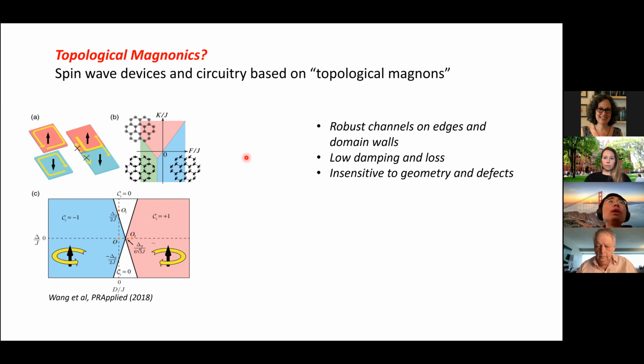This is due to something intrinsic to magnonic systems: in spin systems you have dipole-dipole interaction between spins, which is long range. This long range dipole-dipole interaction can induce a non-trivial singularity at k equal to 0, because it's long range, so after you Fourier transform you get some singularity. That singularity can lead to this situation where you have an edge state higher in energy than the bulk state - something beyond electronic band topology that I did not discuss here.